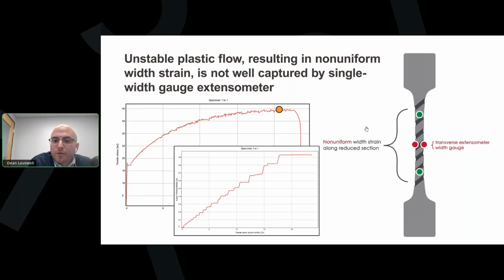You can see that the width strain increases when the location of the strain is specifically at the transverse extensometer's arms, but then it plateaus while this width strain is occurring elsewhere. We know that during these plateaus, the specimen is continuing to strain in its width. It's just occurring in a localized band outside of the view of our single width gauge extensometer.